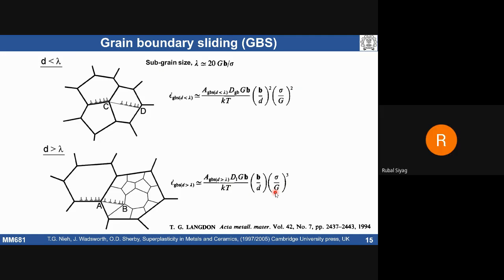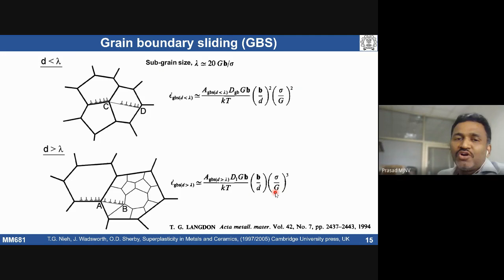What are the benefits of having a coarse subgrain size compared to the grain size? See, when you talk about dislocations, what do you mean by subgrain? A dislocation cell structure has to form, and annihilation should take place. Annihilation of the dislocations leaves some subboundaries like this. So if the subgrain size itself is greater than your grain size, there is no chance of dislocation pile up. Dislocations are not going to be retained within a grain. If the grain size is coarser, then we are facilitating the formation of subgrains.